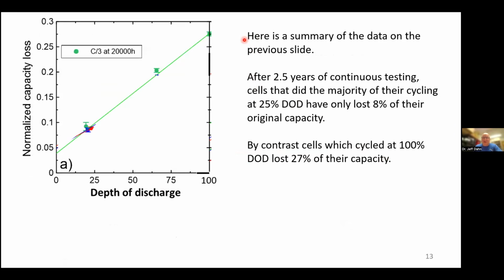This is a summary of the data on the previous slide, which shows the fractional capacity loss as a function of the depth of discharge that was taking place during those cycle tests. You can see a sort of linear progression here. After 2.5 years of continuous testing, cells that did the majority of the testing at 25% depth of discharge lost only 8% of their capacity. By contrast, cells that worked at 100% DOD lost 27% of their capacity.